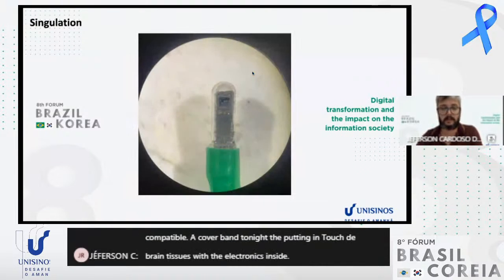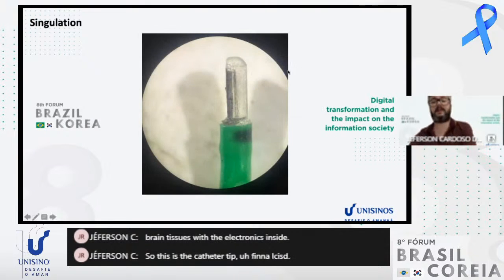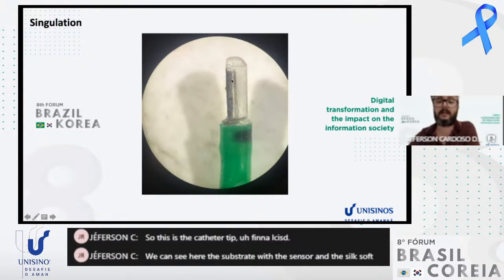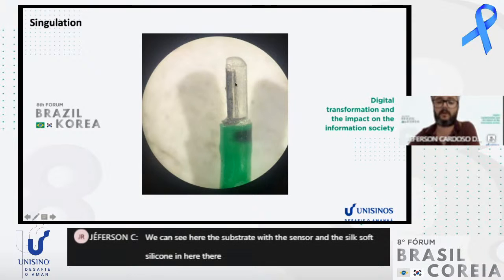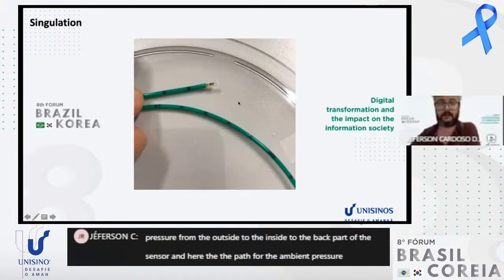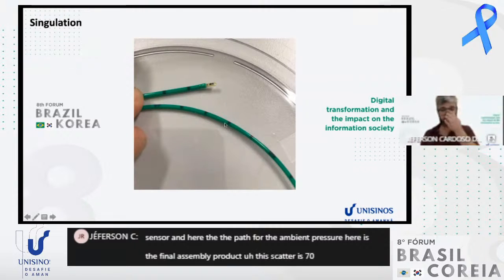So this is the catheter tip finalized. We can see here the substrate with the sensor and the soft silicone. And here there is a venting hole to connect the ambient pressure from the outside to the back part of the sensor. And here the path for the ambient pressure. Here is the final assembled product. This catheter is 70 centimeters in length with a diameter of 1.5 millimeters.